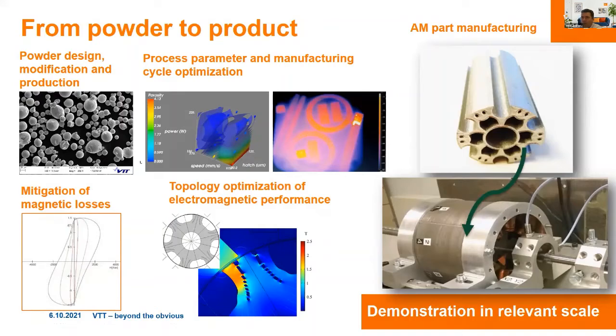And then finally, you have gone through all of those steps. You have designed powder and produced powder. You have correct process parameters, both for the additive manufacturing and heat treatments. You have development strategies for how to mitigate magnetic losses. Then you are able to start the topological optimization of the final shape of the component, and then determine the shape of the additive manufacturing part. And finally, you have made the part, and you are able to start the demonstrations at the selected scale. So this is now an example of VTT pilot scale demonstration facilities in electrical machines.